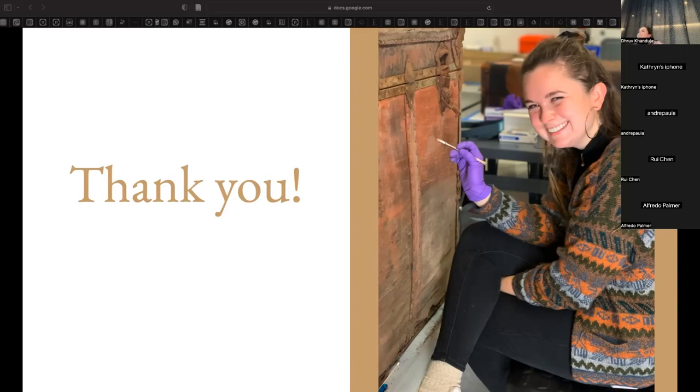This is actually a huge deal for the Technical Studies Lab — if you Google the Vinland Map, we did a lot of work on that project. The map was briefly thought to be a quite old, original map from the 1400s or 1500s, and it was put onto original parchment, so it felt very real. But in analyzing with MacroXRF and other techniques, one of my supervisors saw that one of the inks used titanium white, which wouldn't have been invented until the late 1800s or early 1900s. Things like that — where you have the date of origin of certain materials — allow you to definitively say this has to be fake, because the material wasn't even invented when it was purported to have been created.